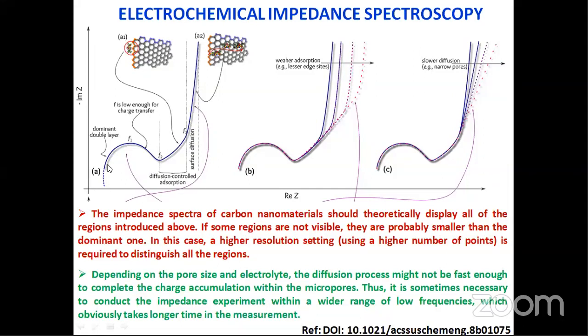Say if you have the semicircular region, it is double layer dominant. If it is extended, you can see that that is due to the charge transfer. Of course, if you have such a phenomenon in your impedance in the practical case, this is diffusion controlled adsorption. So we can't get this portion if it is battery type behavior. If it is a battery, it can have only this part.